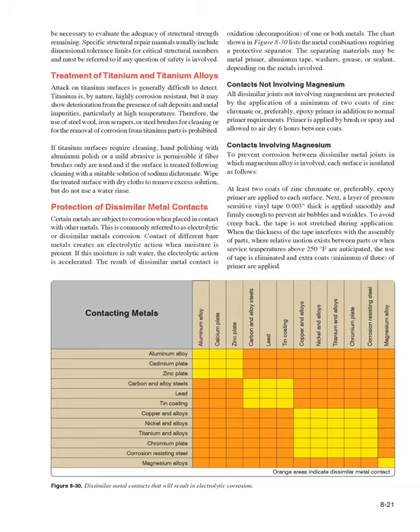The chart shown in Figure 8-30 lists the metal combinations requiring a protective separator. The separating materials may be metal primer, aluminum tape, washers, grease, or sealant, depending on the metals involved. Contacts not involving magnesium. All dissimilar joints not involving magnesium are protected by the application of a minimum of 2 coats of zinc chromate or, preferably, epoxy primer in addition to normal primer requirements. Primer is applied by brush or spray and allowed to air dry 6 hours between coats.